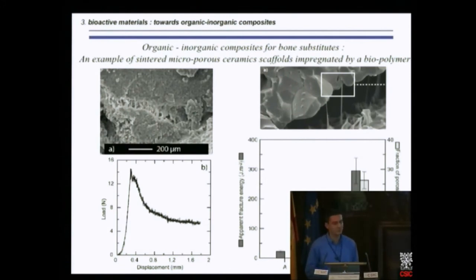Playing with organic matter. So this is an example of a sintered microporous ceramic scaffold which is impregnated with a biopolymer. So the method is quite simple. You have a porous scaffold and you impregnate the microporosity with a polymer, especially biopolymer. And then you make strength measurements. You make some mechanical tests. What we obtain is that here is the ceramic, here is the crack, and you can see some bridges.